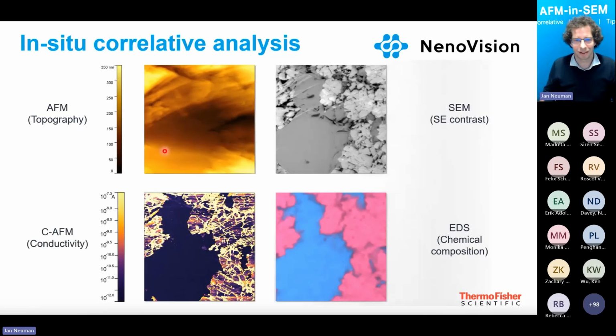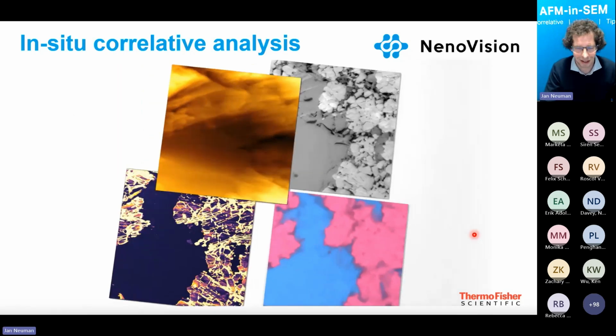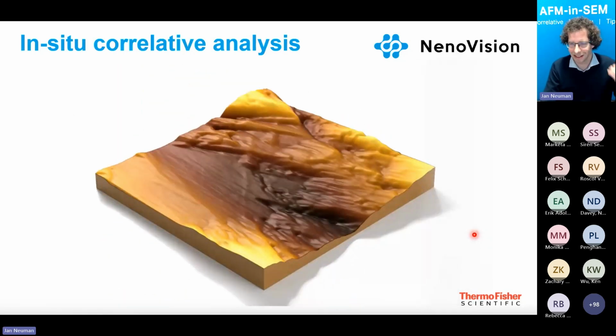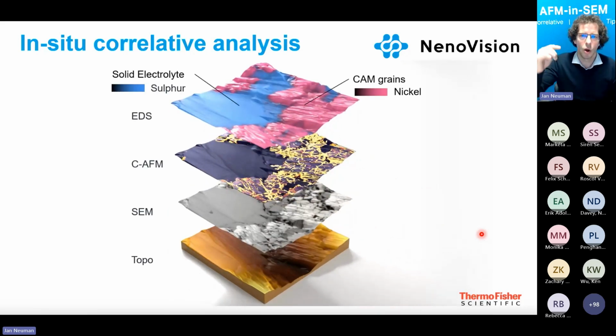We talk about correlative microscopy, so we want to show you how nicely you can correlate all the information from topography, conductive AFM, SEM, and EDX, taken from exactly the same spot under the same conditions. You can put them together, correlate them, and then start to understand what is going on, what's the correlation between the chemical composition, conductivity, surface roughness, etc., which really gives you deep understanding of the processes, composition and properties of your batteries.